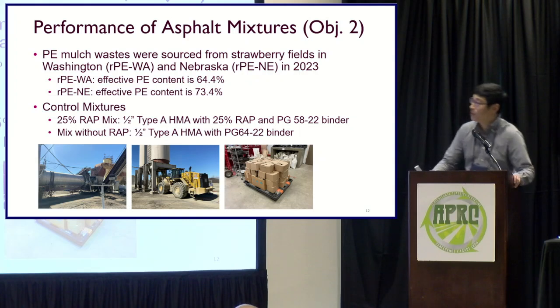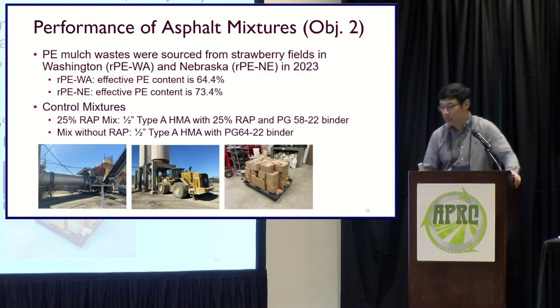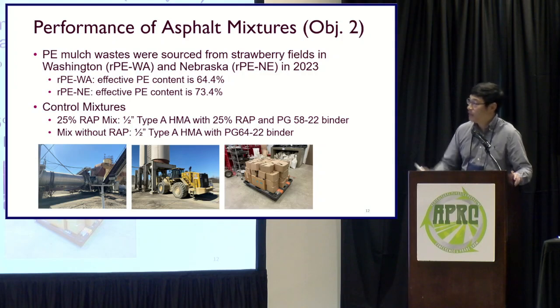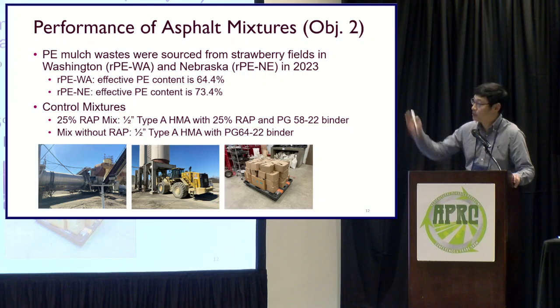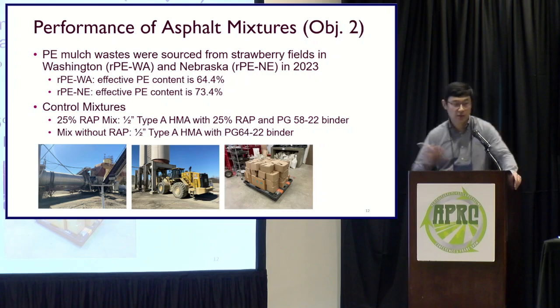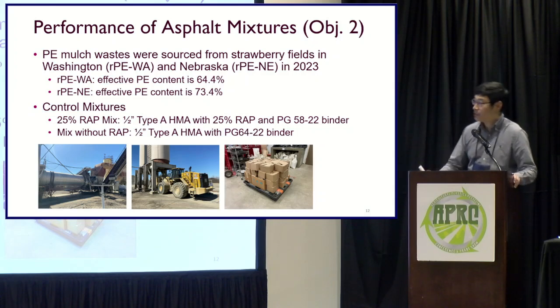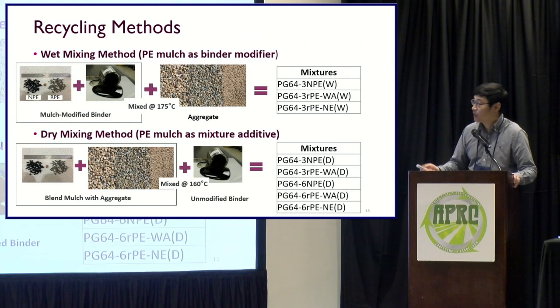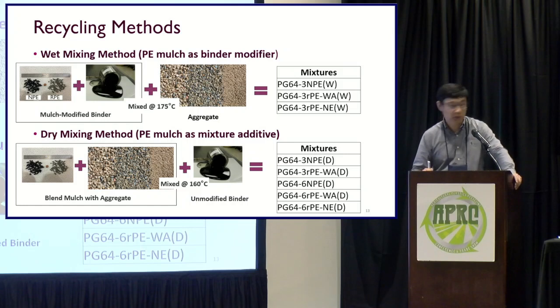Talking about the performance of the asphalt mixtures, we collected the PE mulch waste from the Washington side and the Nebraska side. So we have the RPE-Washington and RPE-Nebraska last year, and they have a different effective PE content. And we collected the control mix. We used a recycled RAP mix, the control mix from the field, and also we designed the mix without the recycled, without the reclaimed asphalt pavement, without the RAP. So that's 2 control mixes we used.